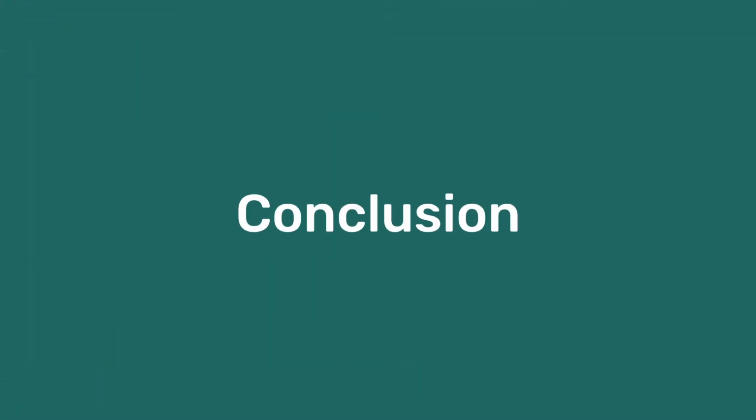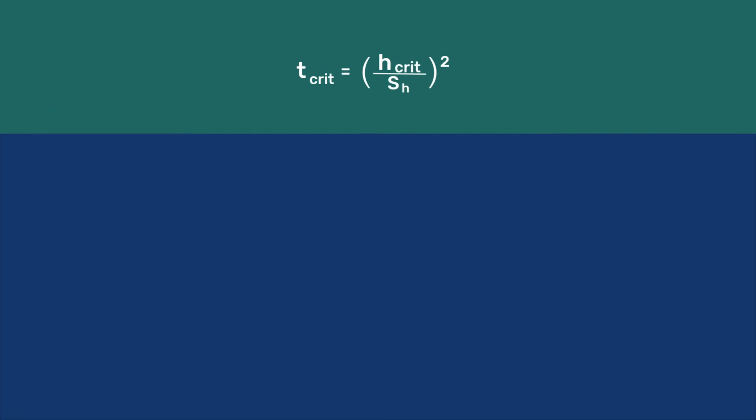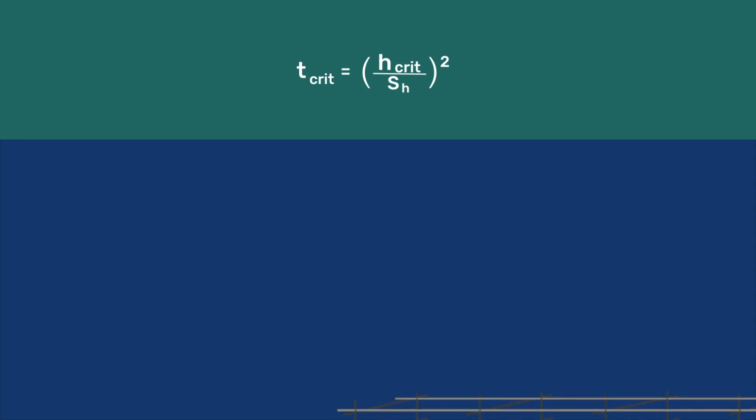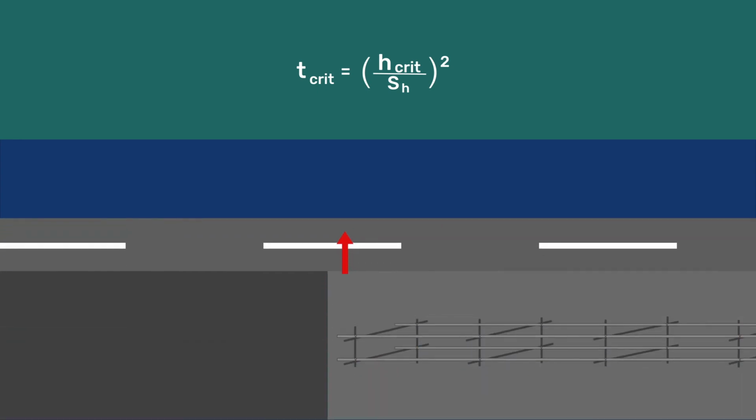In conclusion, the time needed to reach a certain depth of capillary ingress increases with the second power of the ratio between depth and sorptivity. This insight can be used either to select materials or to better dimension structures to increase their service life.